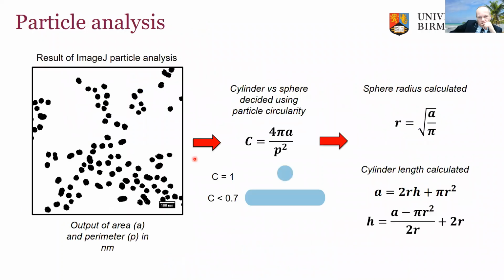And the way that we analysed this, because having done some initial work we saw that we were seeing some non-spherical constructs, so we did some image particle analysis, and we defined the circularity of the complex, which is basically cylinder versus sphere, decided using this formula for particle circularity. If C is equal to 1, we have a spherical particle. If C is less than about 0.7, this means we have an elongated particle. I'm not going to dwell on the maths, but it's important to highlight the C value was something that we were using.